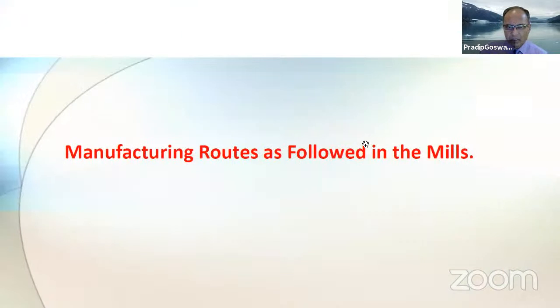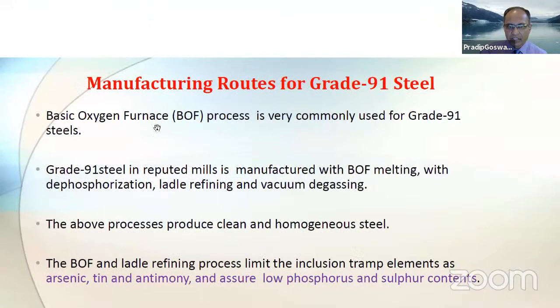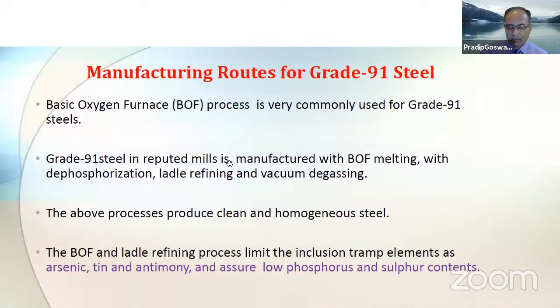Let's have a quick look at the manufacturing routes followed in the mill. Generally, the basic oxygen furnace or BOF is very commonly used for grade 91 steel. Following the manufacture, it goes through special steel making processes like dephosphorization, ladle refining, and vacuum degassing. Each of these processes helps to cut down the gaseous as well as the metallic and non-metallic impurities, as well as so-called tramp elements like sulfur, phosphorus, arsenic, antimony, etc. in the steel. So all these processes produce clean and homogeneous steel.